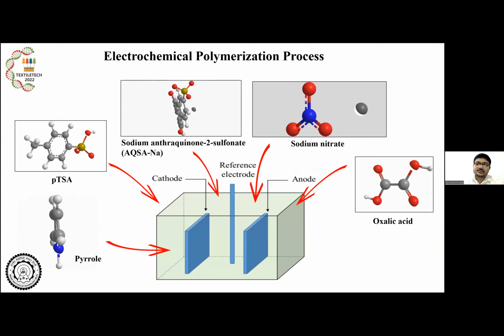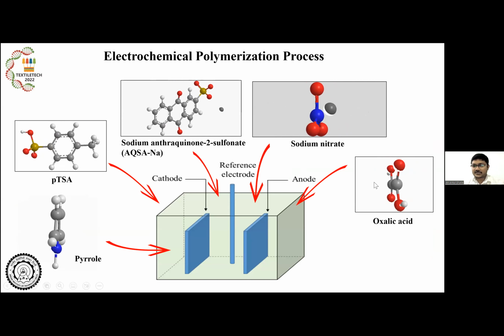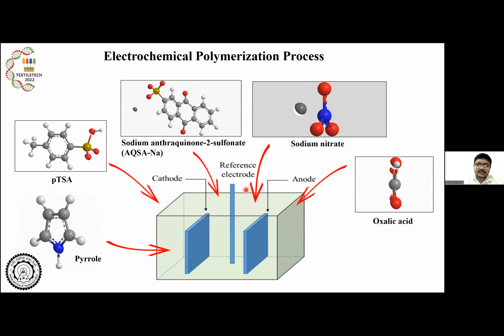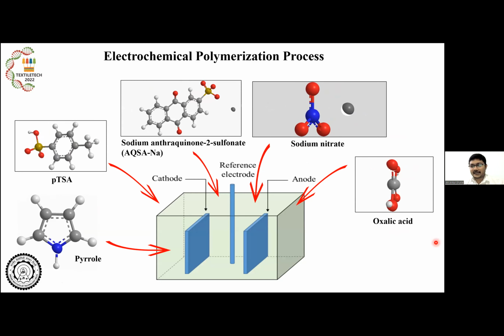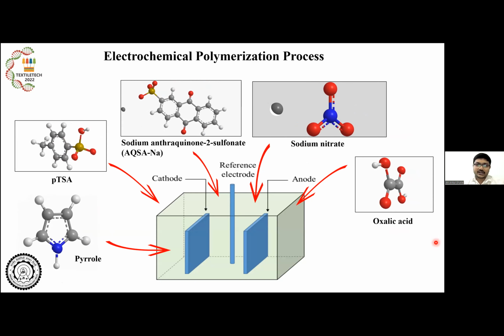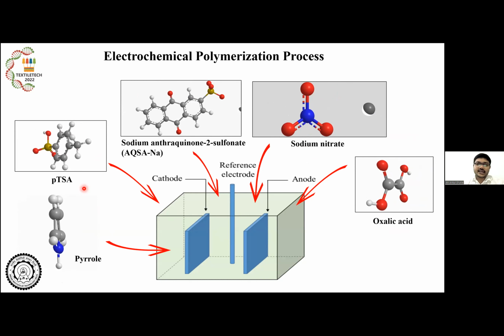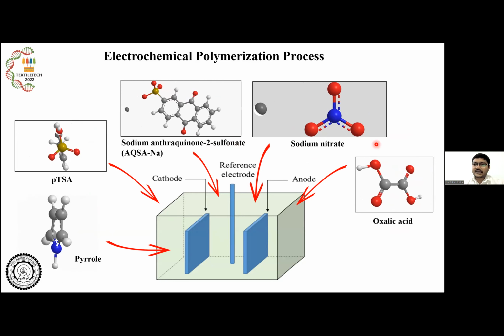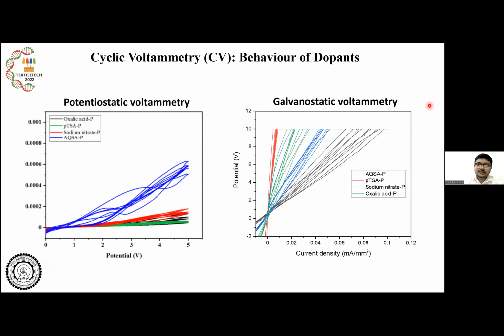So this includes an electrochemical cell, such as shown here, and it includes a monomer. In our case, it is pyrrole. And then we have used different kinds of dopants to increase and to change the conductivity of the polymer formed. This includes PTSA, p-toluene sulfonic acid, anthraquinone sulfonic acid salts, sodium nitrate, and oxalic acid. So to see the properties of these, we have used cyclic voltammetry. It was done in two ways: potentiostatic voltammetry, where the applied potential is varied and the system current is being observed, and the other one is galvanostatic voltammetry, where current is varied and the potential is being observed.